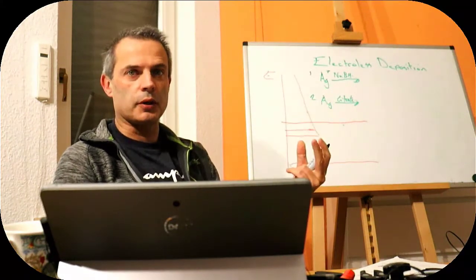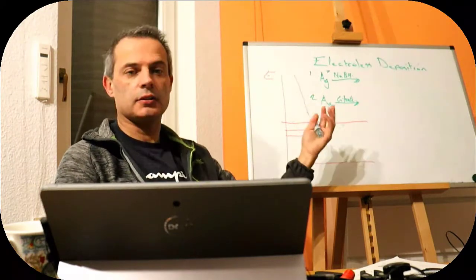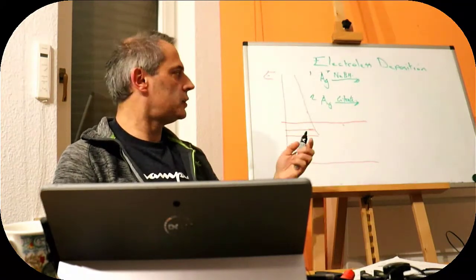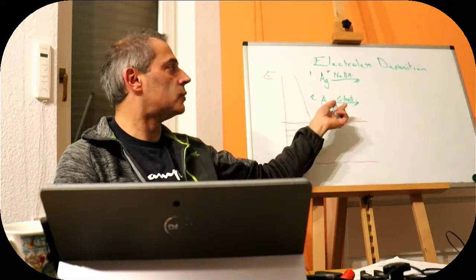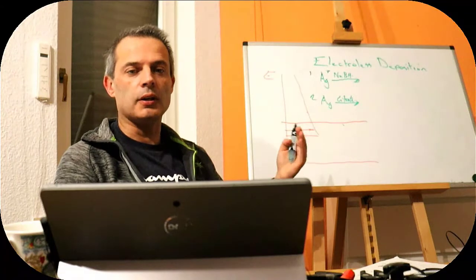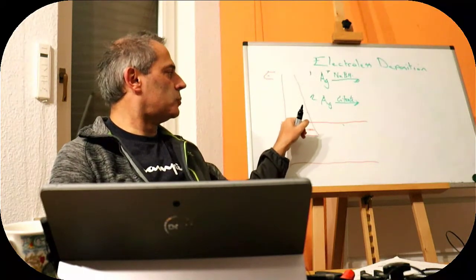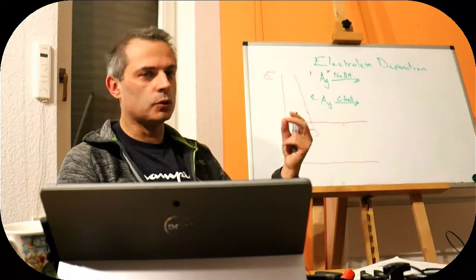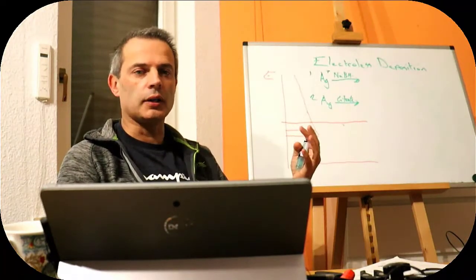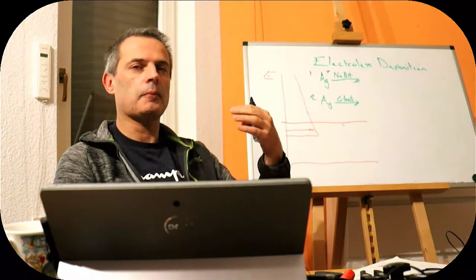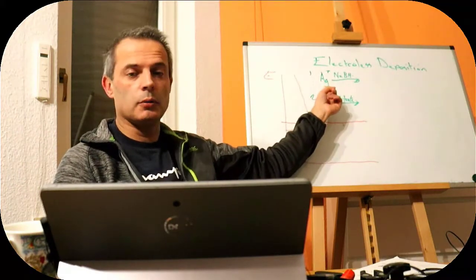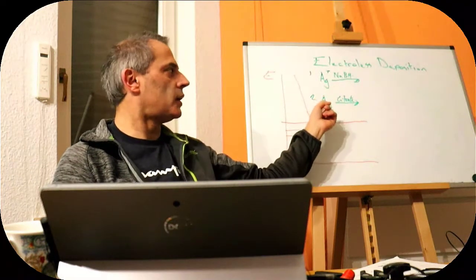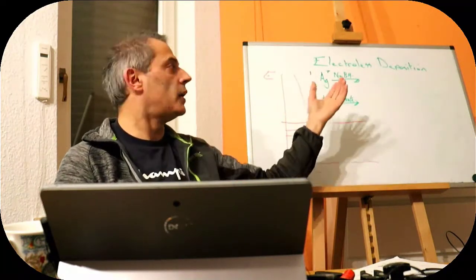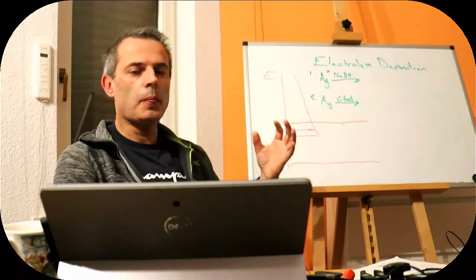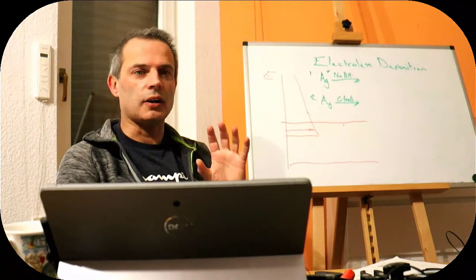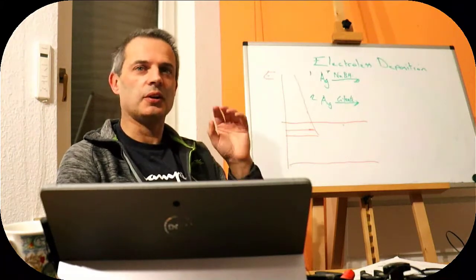If we want to grow those particles, then we can take them out and put them in a second solution which contains a weaker reducing agent, which could be ascorbic acid, vitamin C, or citrate. And citrate is a pretty crappy reducing agent, and it will be somewhere around here. And then it will cause the silver particles to grow. So if we want to make silver particles that are all the same size, the typical process is to first of all make a whole load of nuclei with this process here, and then to grow them with this one here. Obviously we don't have to use exactly these processes, but similar ones are used to make silver particles of